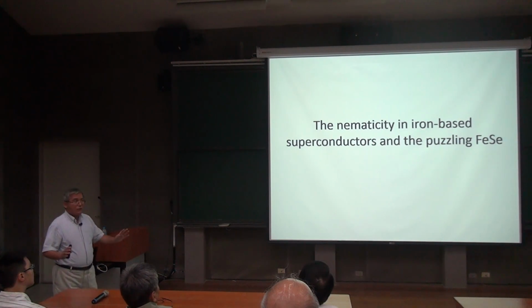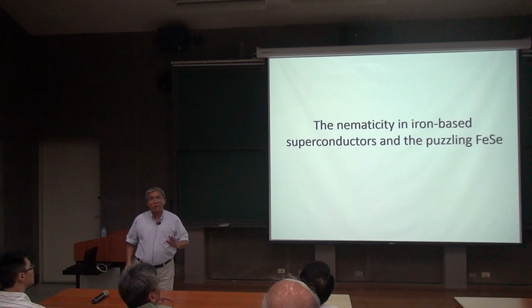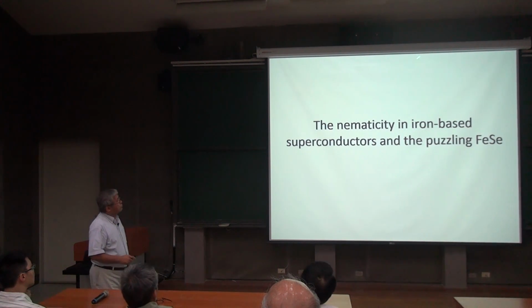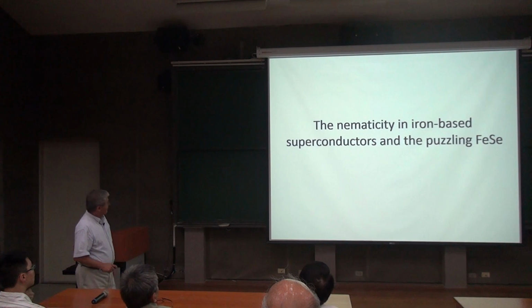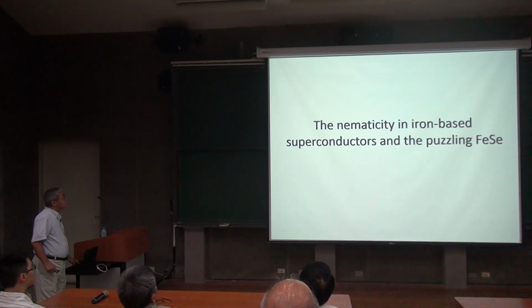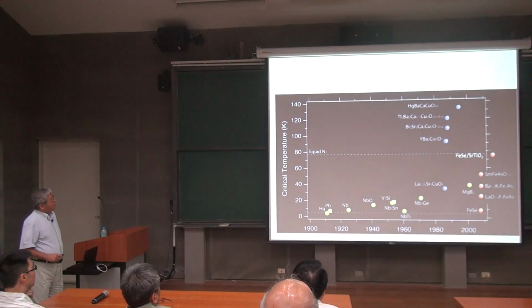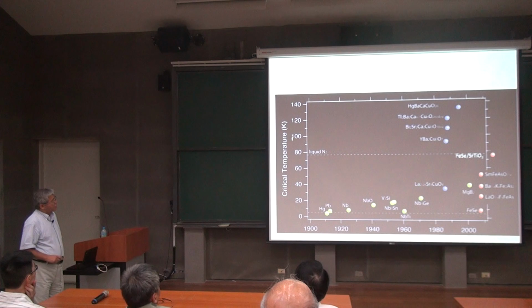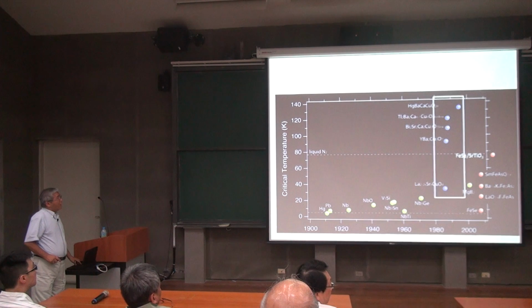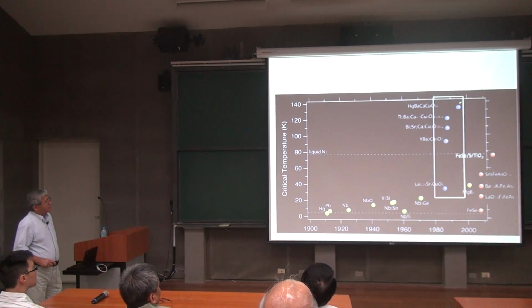So now I want to switch gear to talk about a seemingly totally different subject. Okay? This has to do with high temperature superconductivity. This is a famous historical plot of the critical temperature of superconductors versus time. And there are two milestones. The first occurred in 1986 when Bednorz and Mueller discovered the copper oxide high temperature superconductors. Now at ambient pressure, the highest transition temperature, achieved in the mercury compound, is 135 Kelvin.